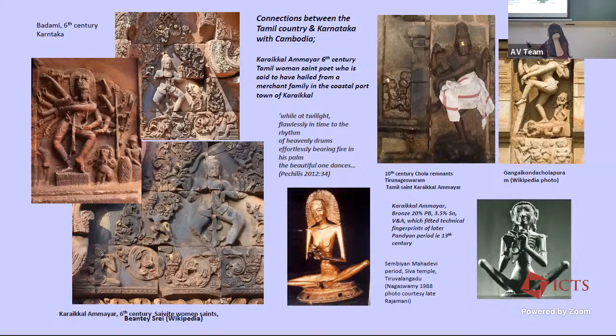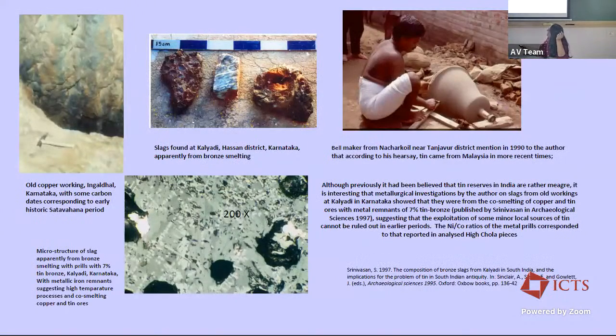And she's playing cymbals. And that is attributed to this famous Chola queen, Sembian Mahadevi. And I was able to analyze this image of Karaikal Ammayar, which is in the Victoria and Albert Museum. This image also fitted the trends of what I would call the later Pandyan period, just before the Vijayanagara bronzes commence. And this had quite a lot of lead in it, as much as 20% lead and 3% tin. So this is just to give an idea of some of what we can do with the analysis.